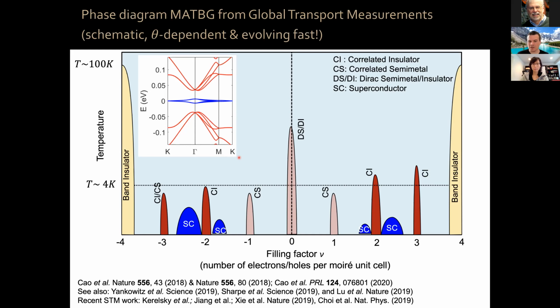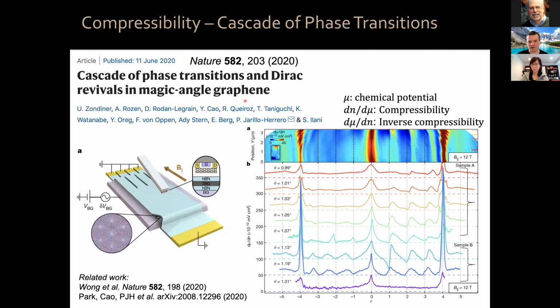And then two interesting studies, one by my group in collaboration with the group of Shahal Ilani at the Weizmann Institute, and another one by the group of Ali Yazdani. We both used scanning probe microscopy techniques. Yazdani used STM, and our group used a scanning single electron transistor to measure the thermodynamic properties of the system. In particular, we measured the inverse compressibility, which is the derivative of the chemical potential with density. So how does the chemical potential vary in your system as you add charge to your system?